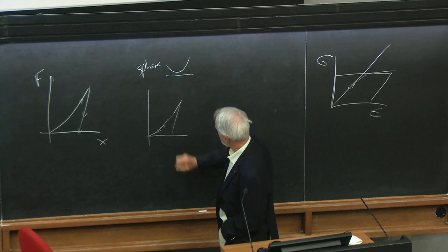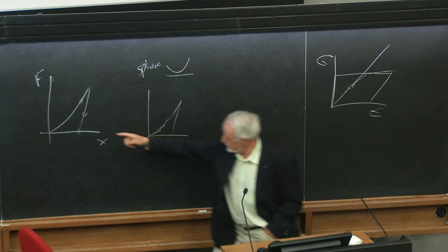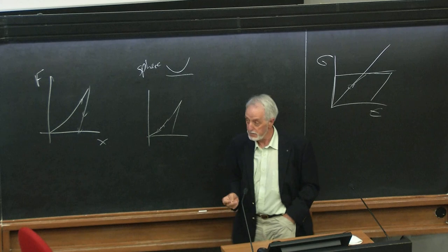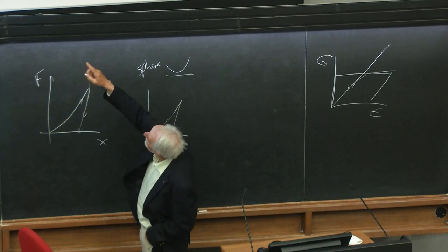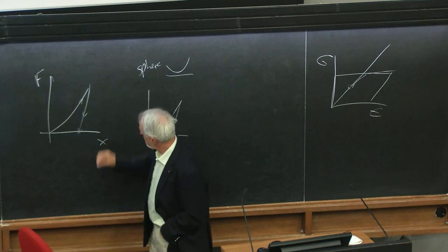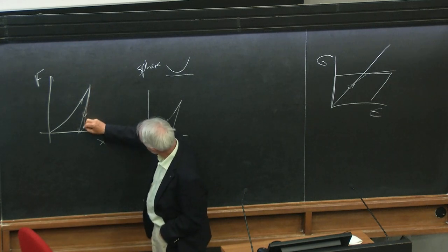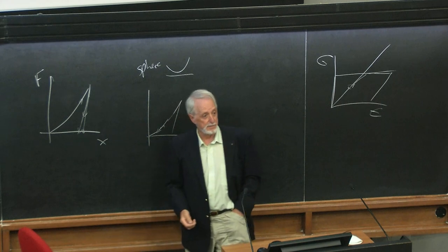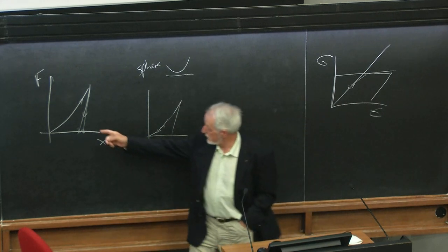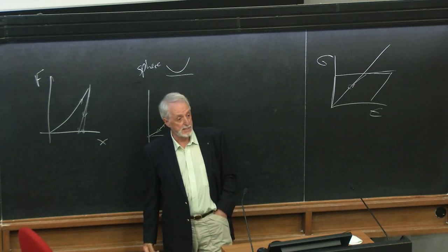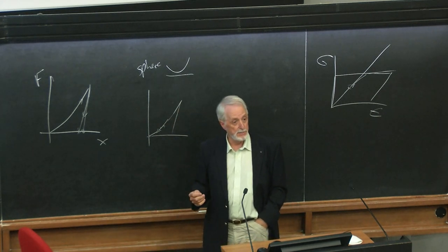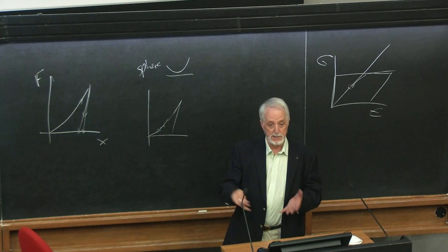But after a certain point, you get some plasticity in the area under this. It tells you something about the total work. And of course, you've got an elastic relaxation here. There's a famous formula there for the stiffness, and of course the depth of the indent. And you can either work out what the elastic modulus is, if you know what the tip shape is, or if you know what the elastic modulus is, you can calculate the tip shape.